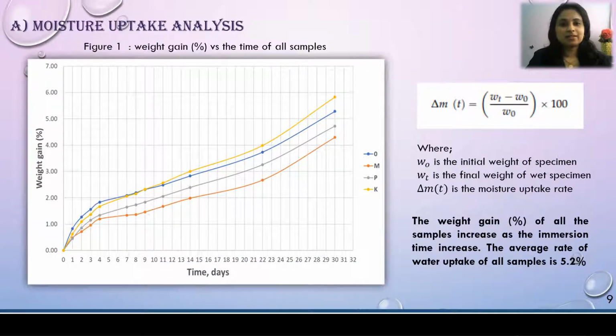The first analysis is the moisture uptake. The moisture uptake percentage, also known as the weight gain percentage, was calculated using equation 1. This graph shows the weight gain percentage versus time of all the samples. From the graph, it is found that the weight gain percentage of all the samples increases as the immersion time increases, and the average rate of water uptake of all samples is 5.2%.